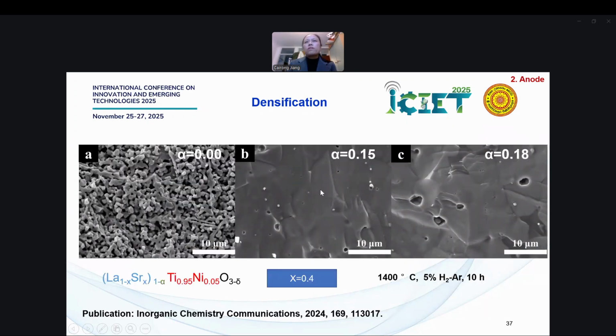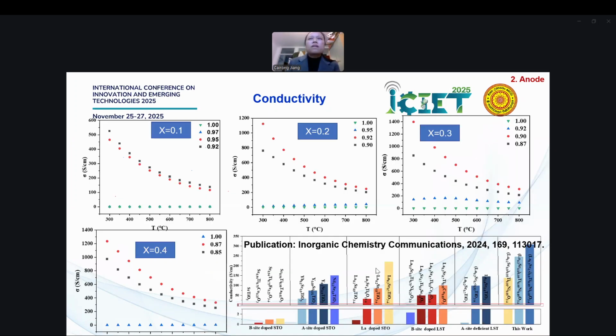You see, we can get quite dense materials at quite low temperature, 1400, where maybe it's a normal temperature to prepare a whole cell. Because whether it's electrolyte supported or electrode supported, we often have to go high enough to make sure we can get a dense electrolyte to get a good cell. And another thing, the conductivity, we have got a good conductivity here. You see, for the 10% and 20% and 30 and 40%, we always get from a few hundred Siemens per centimeter to 1,000 Siemens per centimeter. So it's a good enough value for solid oxide fuel cell anode.